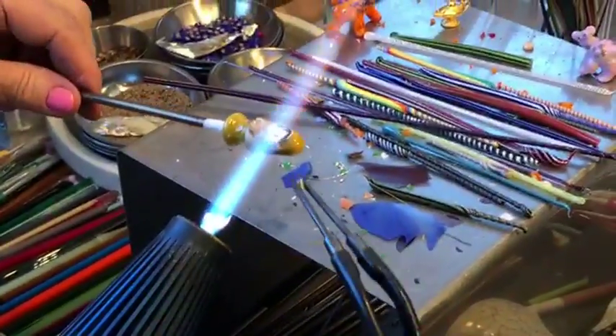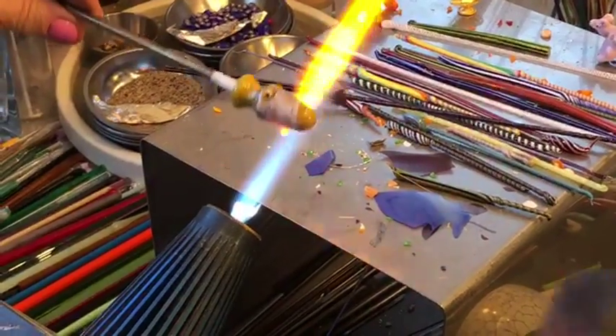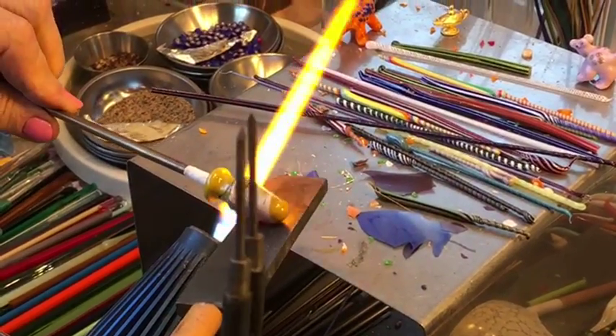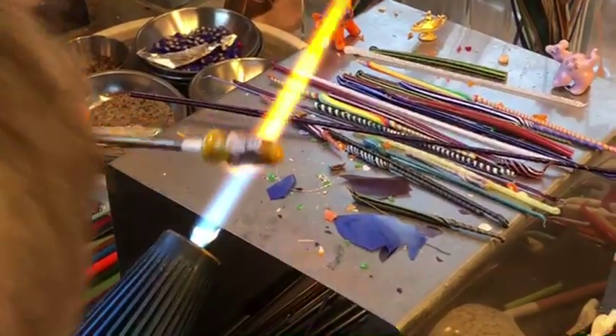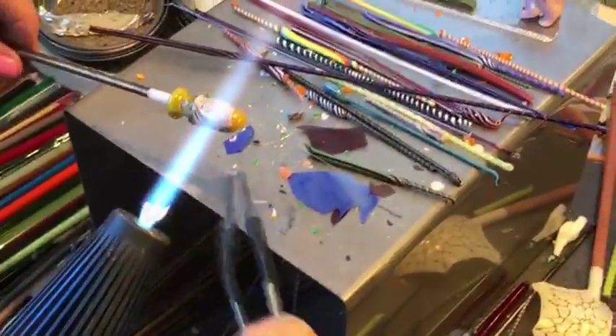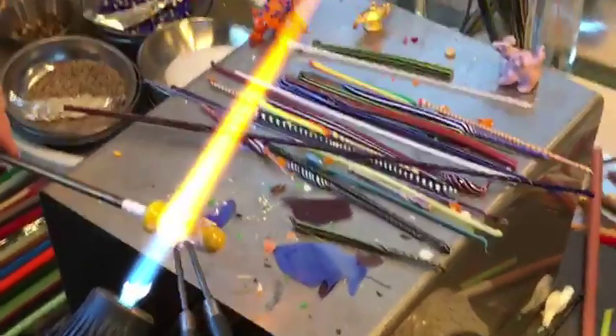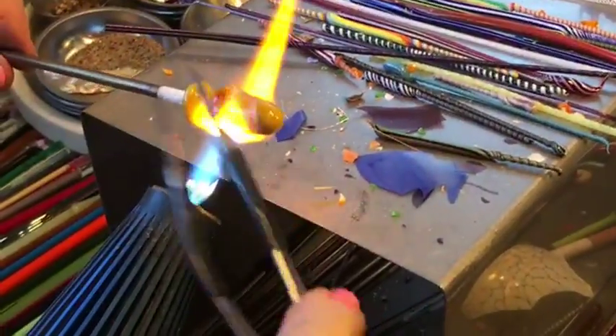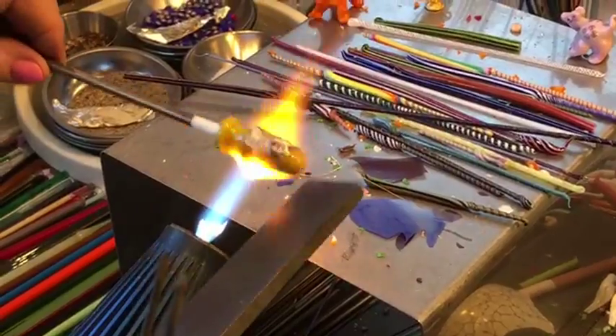I think I'll use this one — we're doing quite a plain little bottle. Heat it up, squish it flat, roll it in, don't lose the shape of the rest of it. Here's another one — get a grip on that little piece. Flash it in the flame. Flashing it in the flame warms it up so that when you put it in the flame it doesn't break into lots of little bits. If you just put a cold piece in the flame it would explode — it has to be pre-warmed.